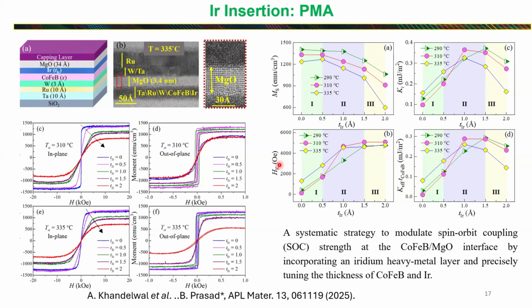What we found is that typically people use around 335 to 350 degrees centigrade for annealing this MRAM stack. But at 335 degrees, the iridium diffuses inside your ferromagnetic metal, and hence you lose the magnetization. Because of that, your Ki goes down, and you also don't get a very high VCMA. So the best is to reduce your temperature. We optimized this annealing temperature and found that 310 degrees centigrade is right. With the optimum thickness of the iridium, you can get a high VCMA coefficient as well as high PMA.